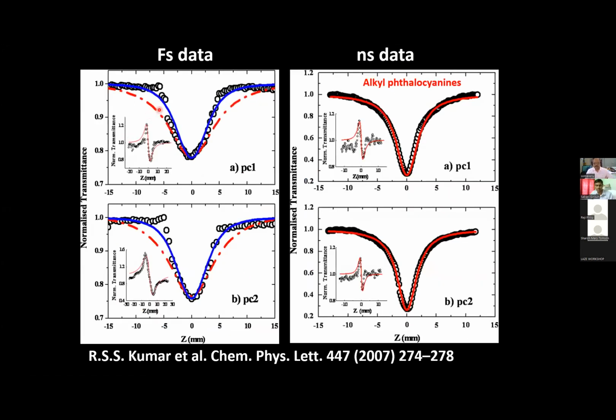So we did both nanosecond and femtosecond. And in femtosecond, you see this is 3-photon absorption. This dotted line is a 2-photon absorption. So depending on the pulse duration and where you're exciting, nanosecond you excite at 532, femtosecond at 800. So 800 gives rise to 3-photon absorption in this material, same material, but with femtosecond pulse.